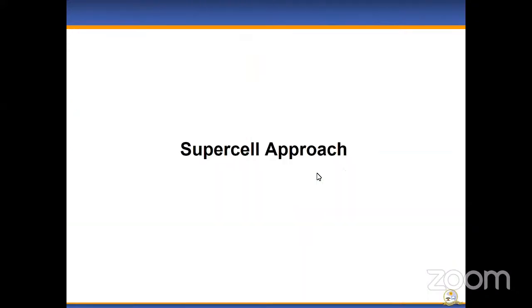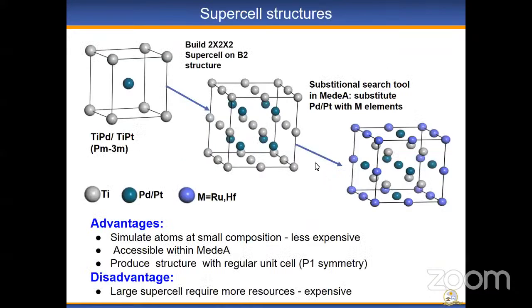Now, I'm moving straight to the first approach that I want to share with you, which is the supercell approach. The supercell approach starts with a single unit cell, which can then be multiplied into a 2 by 2 by 2 unit cell, and then you increase it as much as you want. What I want you to note is that when you use the supercell approach, to deal with smaller atomic compositions or concentrations, one will need quite a big supercell to do those doping, mixing the atoms together.